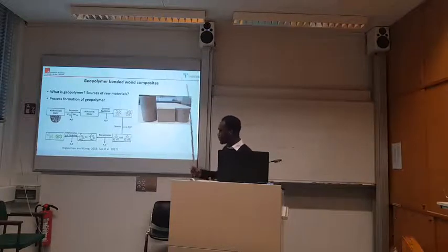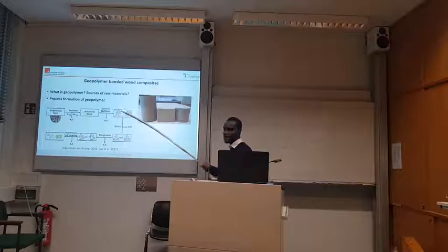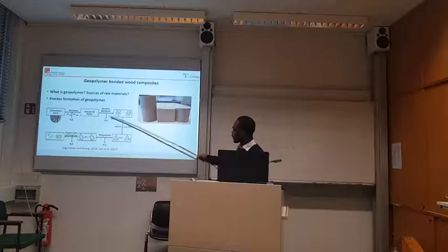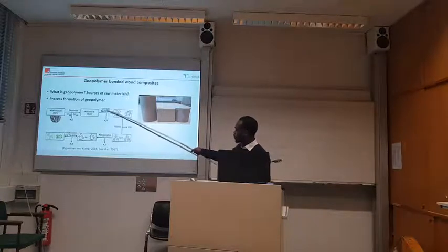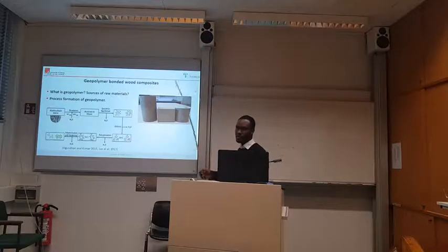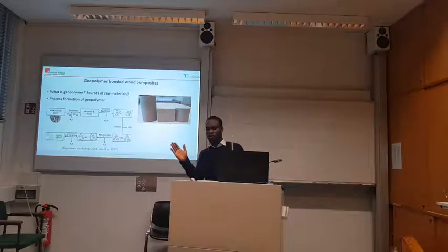rearrangement of the species. With the rearrangement of the species, they are still in the liquid form, so the reaction is still ongoing. Then with the rearrangement, from there, we have water coming out to the rest of the process. The difference between this and the cement reaction is that with cement, we are consuming water. So the more water, the more solid and hardened it gets.